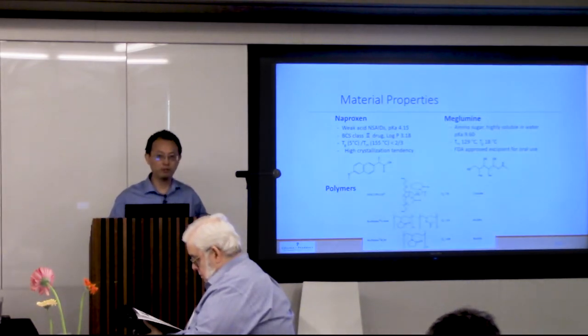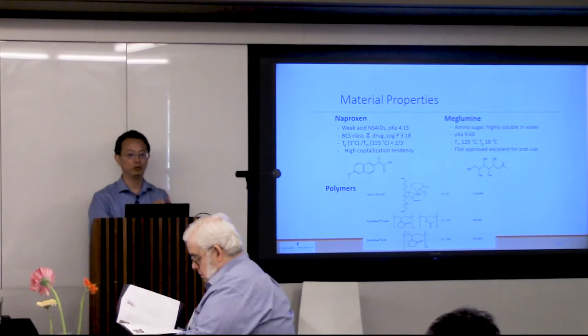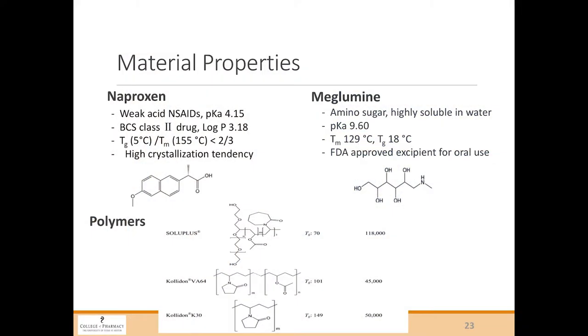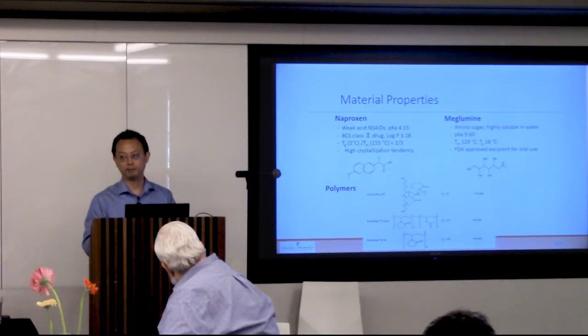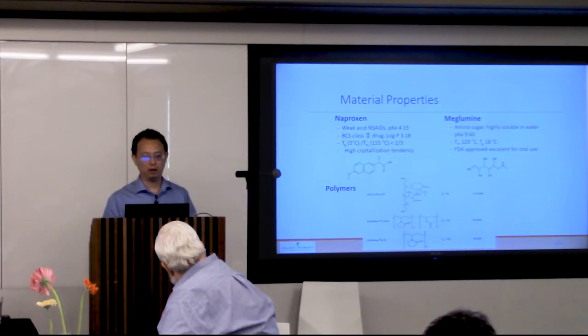But naproxen amorphous dispersions have some issues. Naproxen crystallizes very, very quickly. It's very hard to maintain and keep stable. Part of the reason is that you've got two benzene rings that will stack on top of each other, and you have two carboxylic acid groups forming hydrogen bonds. By itself, you could not make amorphous naproxen, either using melt quenching or spray drying. It's very, very difficult.